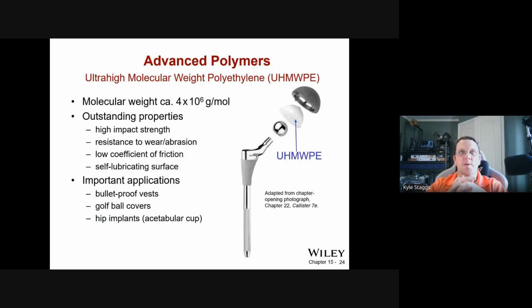Medical implants are another big one. So things like ultra high molecular weight polyethylene, which is a good example, with a molecular weight of about 4 times 10 to the 6 grams per mole. There are some really great properties to leverage, and there are things available that are made of that material. Some are common items, but they're used very heavily in medical applications, where you need high impact strength, resistance to wear and abrasion, a low friction coefficient on the surface, and self lubrication.